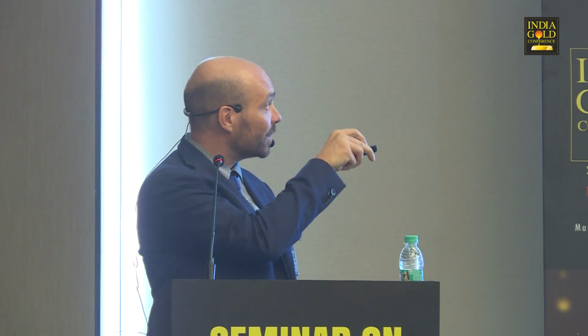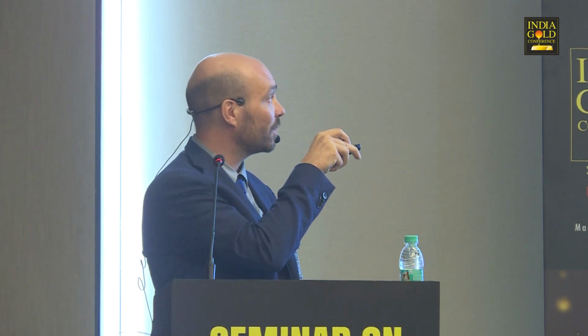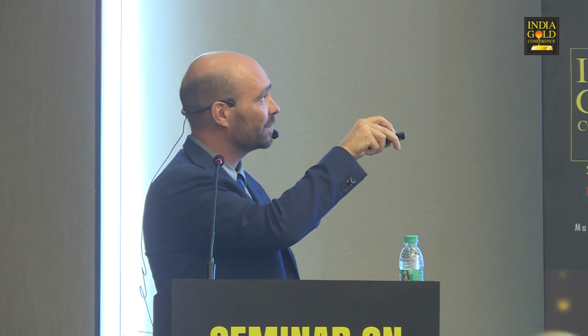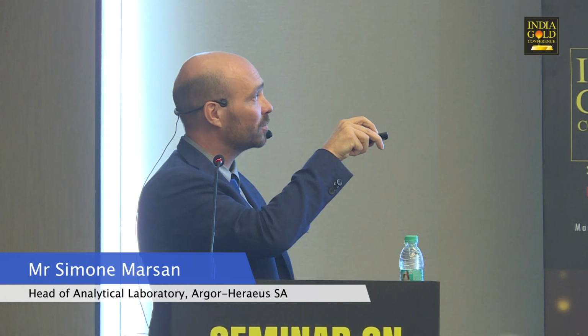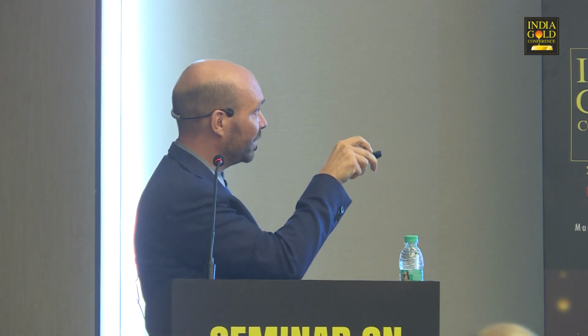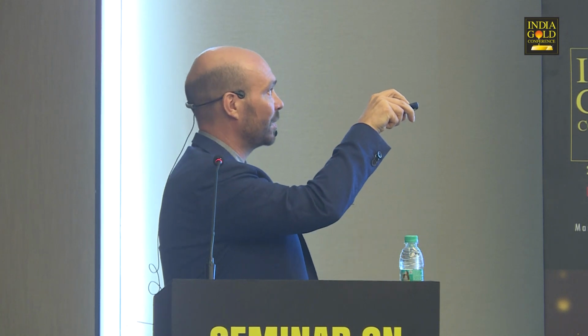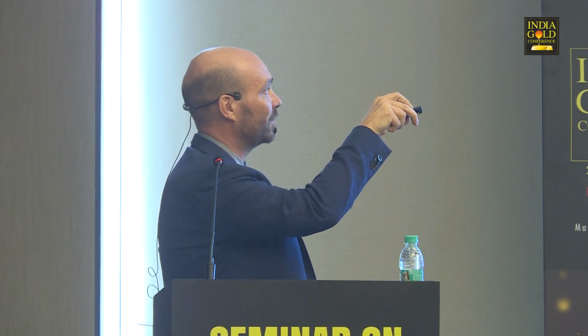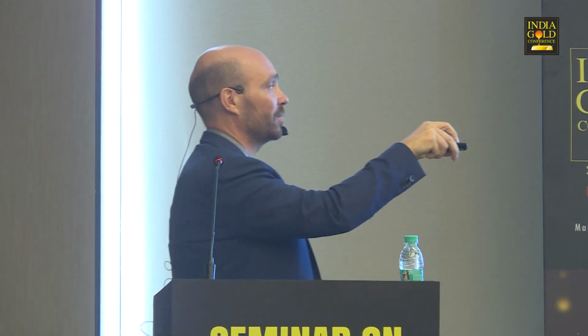No, but you must be sure that you have a flat surface and you don't have cracks inside, because some drops of metal can go down in the cracks, and you will get some loss of material. But these are better not because of the quality, but because they are square, and you must control the position in the muffle better. If you put these 36 cupels inside the muffle, you have to look at the position, and maybe you can make some error. For example, this one is at a different depth from this one. And because you are doing correction using proof tests, the position of the proof test is fundamental in this case.